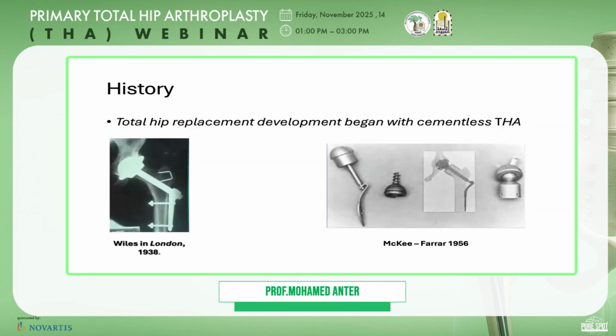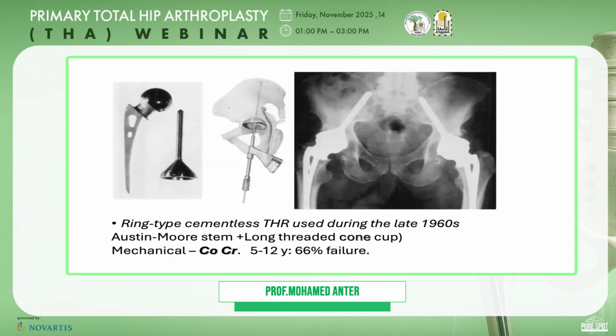For the history, the total hip replacement actually started with uncemented implants, not cemented. The first one was done in London by Wiles in 1938, as you see here, and the second was by McKee and Farrar in 1956. After this, we came up with the ring type cementless total hip in the late 60s, which was an Austin Moore stem over a long threaded cone cup. However, it has a 66% failure at 5 to 12 years follow-up.